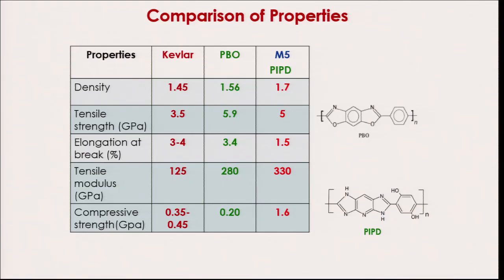In the case of Kevlar, there is hydrogen bonding between the NH and CO group, interchain hydrogen bonding, right. And in the case of PBO, there is no hydrogen bonding between the polymer chains, interchain hydrogen bonding is missing. So, therefore, PBO has a compressive strength which is lower than Kevlar. But the moment we go to PIPD,